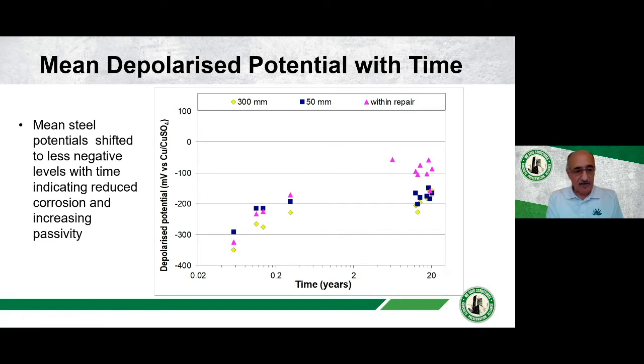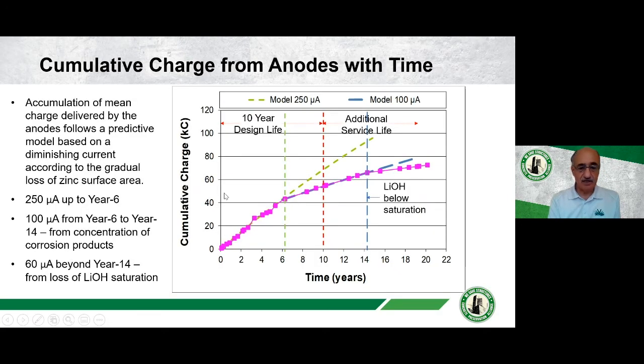One of the other measurements that we were taking was to measure the potential of the steel, both when the anode was connected, when it was disconnected as the instant off, but also 24 hours later. We call that the depolarized potential. You can then determine the depolarization potential between time 0 and time 24 hours. But we were very interested in the depolarized potential, which we took to be roughly the rest potential of the steel at that point. And we could see that with time that potential was rising. It became less and less negative, and we've reached potentials which are believed to be passive, i.e. the steel is no longer corroding when you have potentials less negative than minus 200.